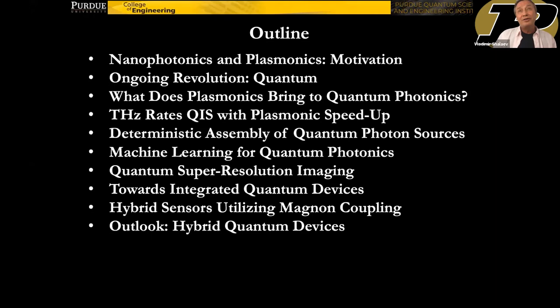The other very promising class of plasmonic materials is transparent conducting oxides. And the beauty of those materials is that they are tunable and switchable, and you could control them simply through doping, and you could do it optically or electrically. They also have wonderful optical properties, for example, epsilon near zero at the telecommunication wavelength, which again is of special importance. And when epsilon is close to zero, you have a dramatic enhancement in nonlinear responses, what we call near-zero-index enhanced nonlinear optics. So yes, the answer is that using new materials makes a huge difference.